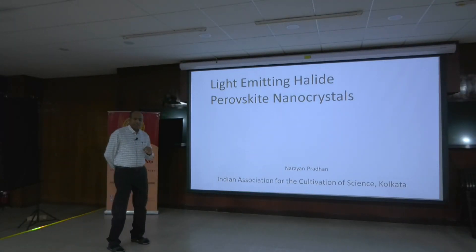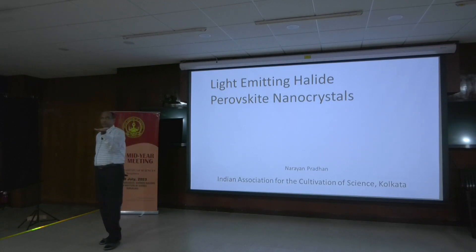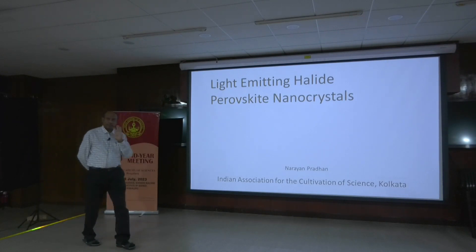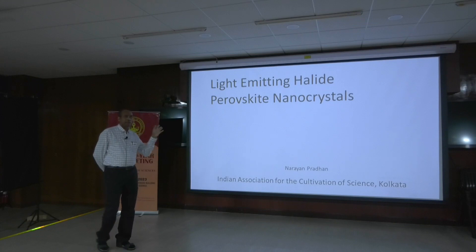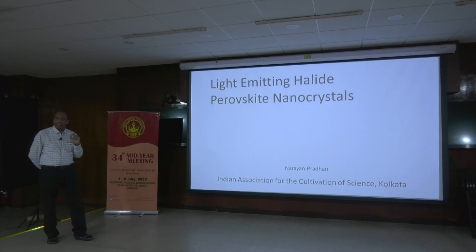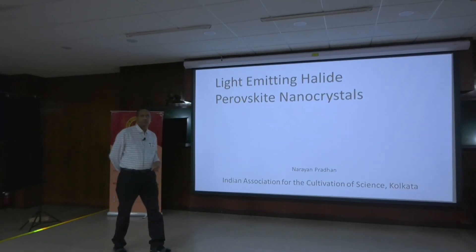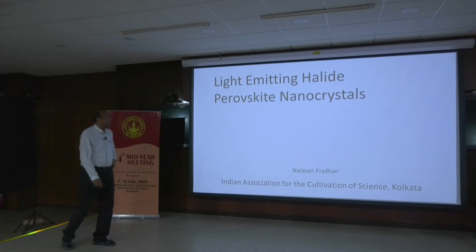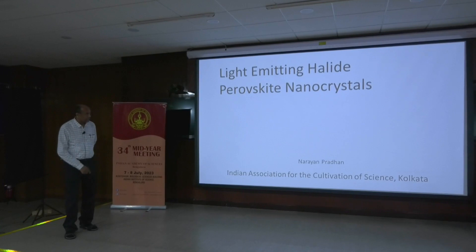But the problem with these nanocrystals is that they are ionic, like sodium chloride. When you open it out, it absorbs moisture. That is the major challenge - how to stabilize this. Importantly today, I am going to talk about ionic crystal modulation, which is not as easy as covalent crystals like zinc oxide or cadmium sulfide. The crystal engineering of ionic crystals is my major talk here.